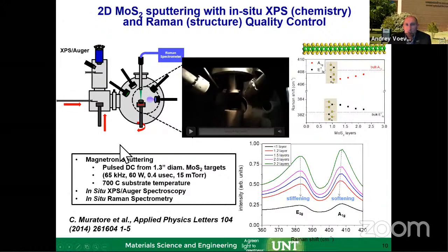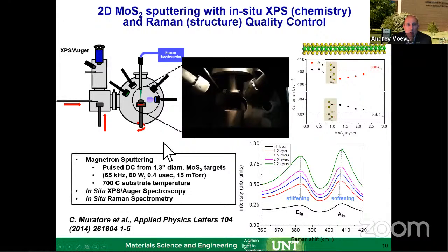So in terms of how this whole process works, you have a substrate on the bottom and the molybdenum disulfide target on the left here. You switch it on and sputter the molybdenum disulfide, which directly deposits here, and it grows for a few seconds and you're done. The process takes just a few seconds, and then you need to analyze it. For analysis, we're using a Raman spectrometer, which is very sensitive to breathing modes or vibrations in molybdenum disulfide in the planar and perpendicular directions. Because these are two primary vibration modes, they will appear in a Raman signal as two peaks.